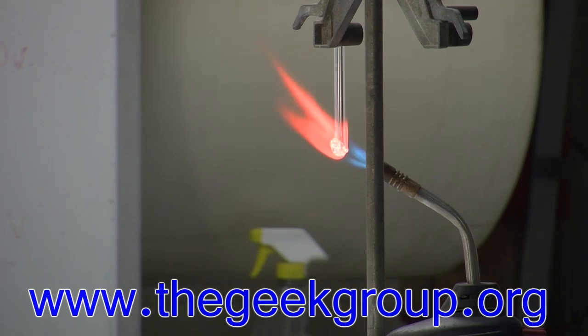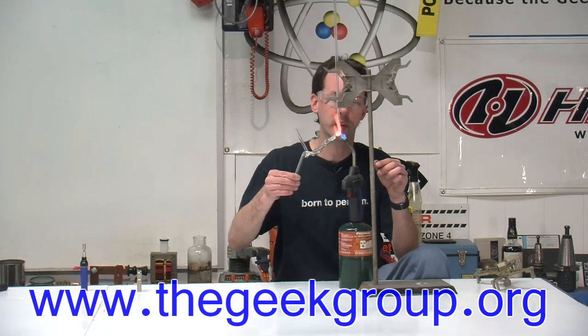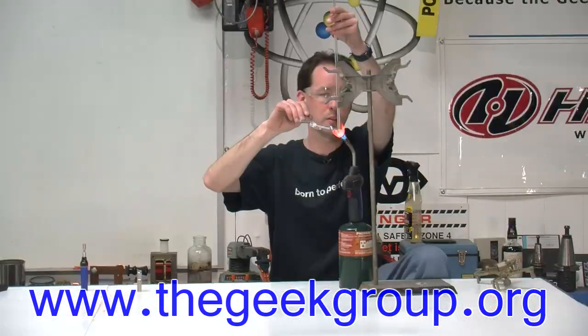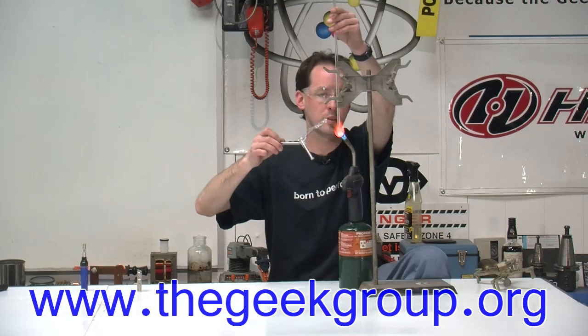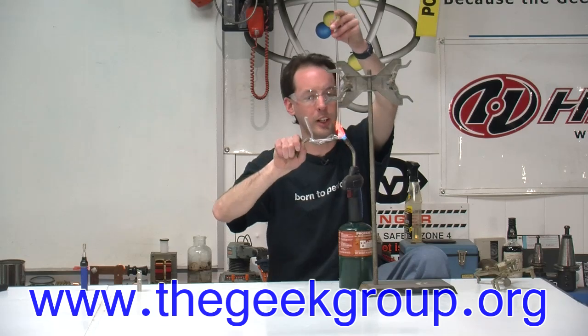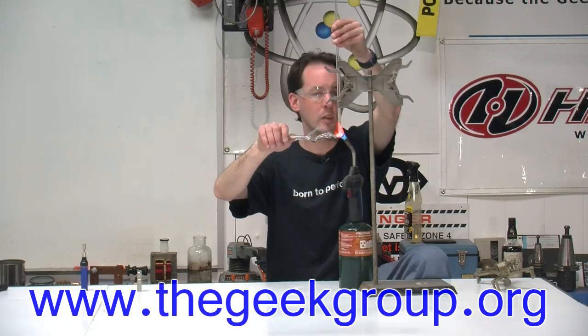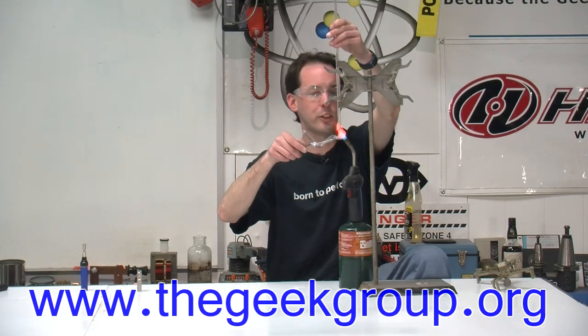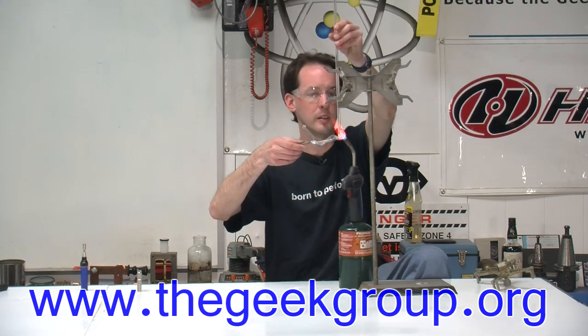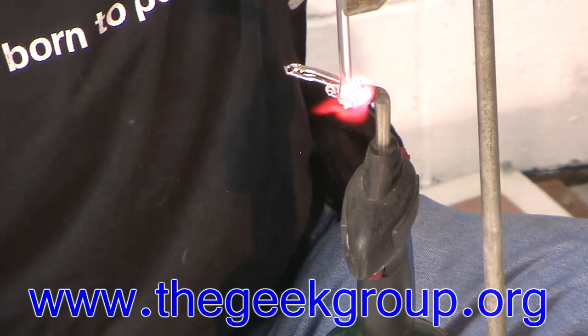I don't think I have enough weight there to get it to drip. So we'll add to our blob. We're just gonna add a big blob of molten glass here on the bottom. The problem is, when you get a big blob, it heats unevenly, and it will crack, and there's nothing you can do about that. I hope I can get this to crack off. There we go.